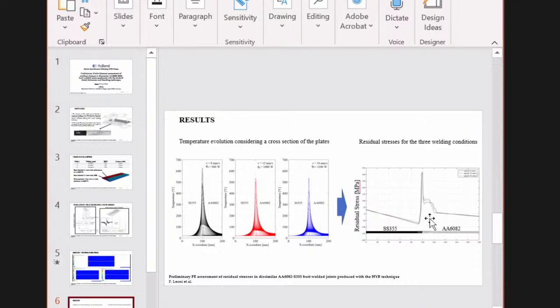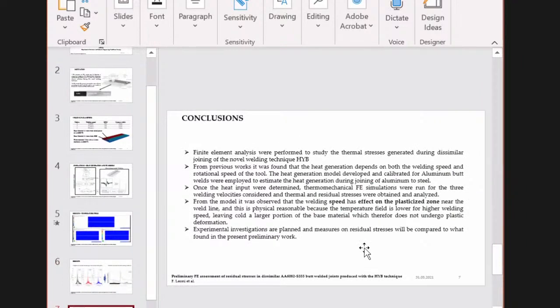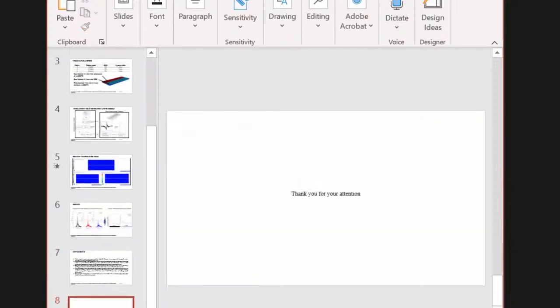The residual stresses are here finally plotted. And as you can see, there is a small area in the steel that is plasticized, and this is due to the high temperature that the material undergoes in the vicinity of the interface. Instead, on the aluminum side, the plasticized zone is a bit wider, I would say, and this phenomenon is to be expected for the three welding speeds, since a wider zone for lower speed comes from the fact that the temperature field is wider for lower welding speed. So to conclude, those preliminary finite element results will be used for future investigations, where experiments will be run. So this is basically what we studied, and thank you for your attention.